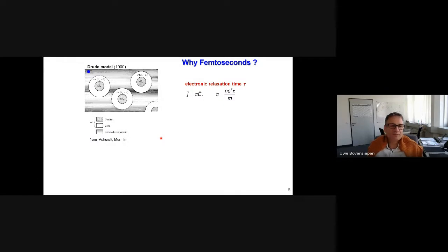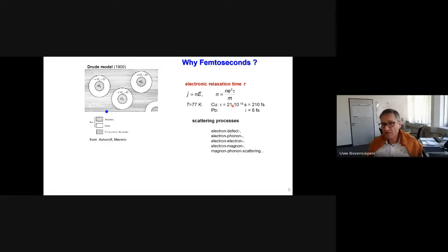We can have another approach to the femtosecond timescale, which also dates back more than a century to Drude, so 1900. And Drude described the electrical current density proportional to the electric field by the conductivity. And Drude's contribution was that he said the conductivity is proportional to an electronic relaxation time tau, and there are constants which are material constants. And Drude described this electronic relaxation time as the time between individual scattering processes of electrons with ion cores. I mean, nowadays we know that this is not the correct description, but what is interesting is the following.